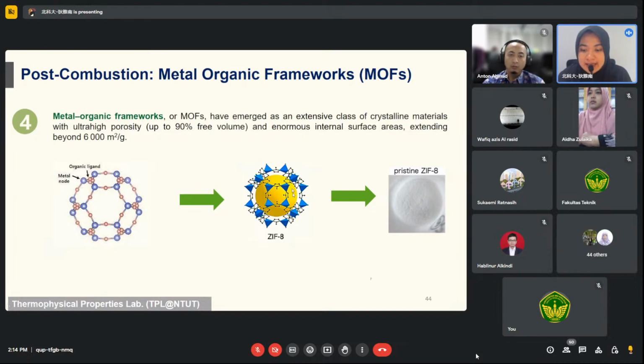And also here we can see a typical metal organic framework. Why do we say metal organic frameworks? Because it consists of metal knots and organic ligands. The red color is the organic ligand, and the blue or purple one is the metal knot. So basically it's like a framework, like kerangka. Inside the framework we can fill in something, probably CO2 gas or CO2 hydrate. So it's possible they will fill inside this pore, and the pore is very small. That's why the surface area is really huge for the metal organic frameworks.